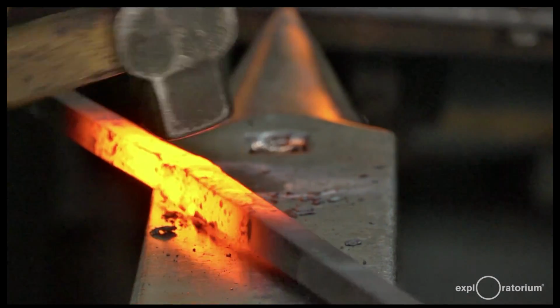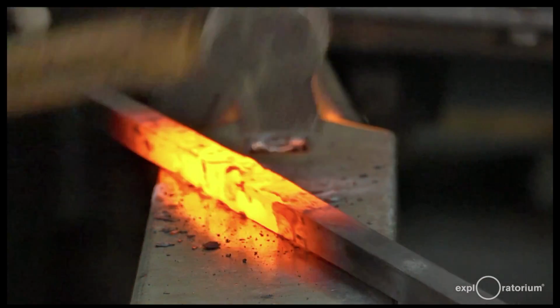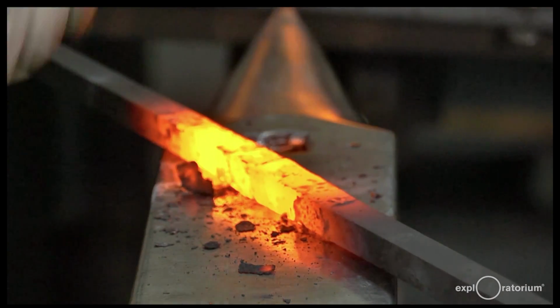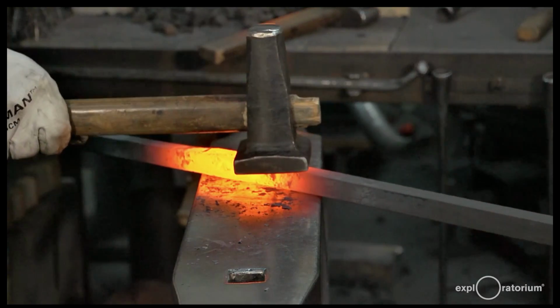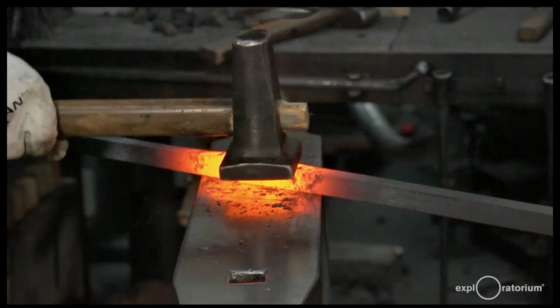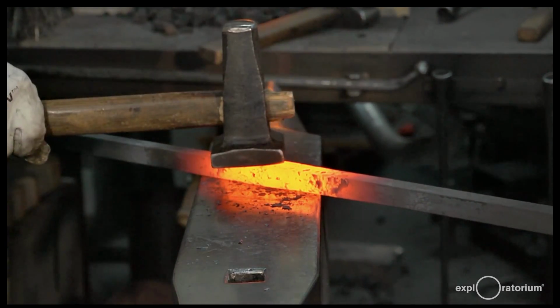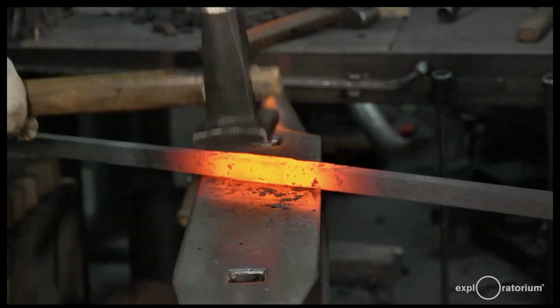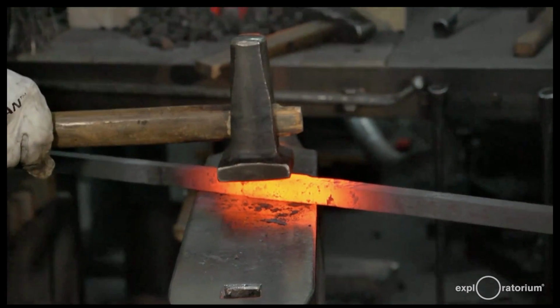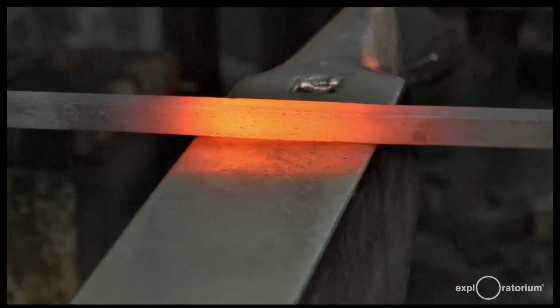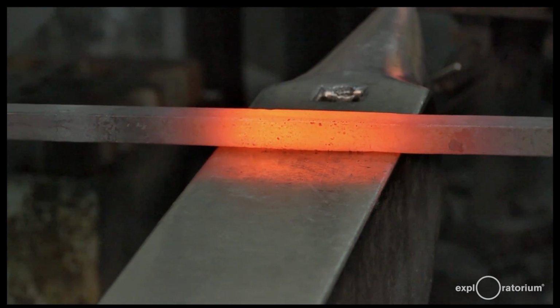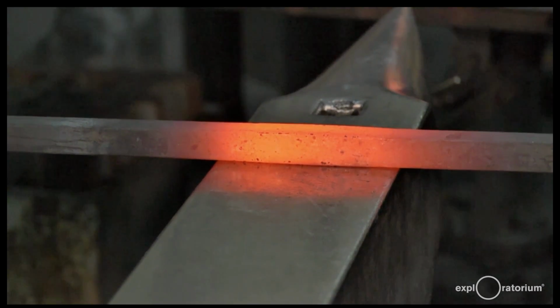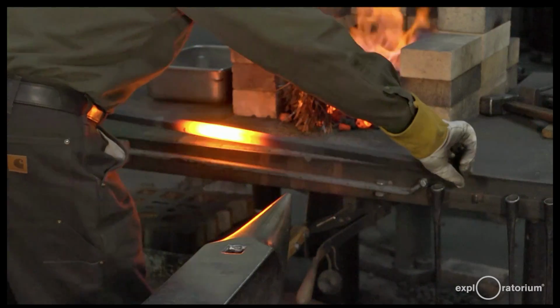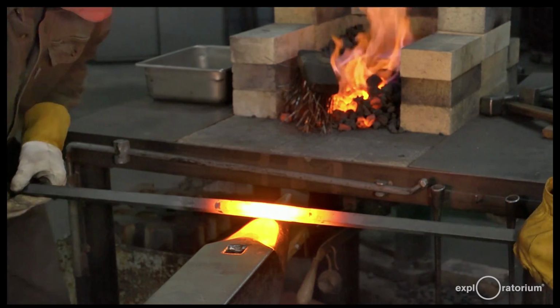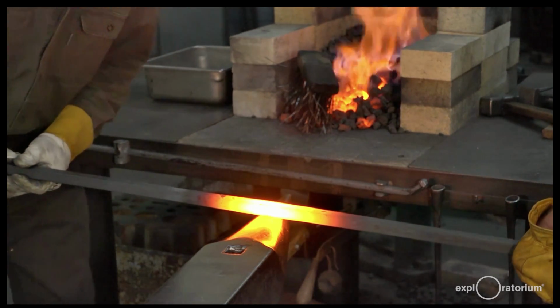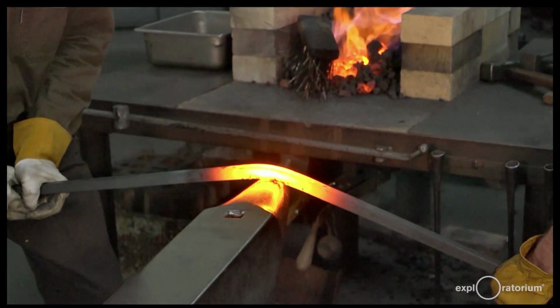After this, we'll be using a tool called a flatter and a sledgehammer to make a much more even shape out of it. And there's the finished weld and the finished bar, and you can see that there's almost no trace of the original seam left. So we'll test it now for you just to help you see what a thorough bond this is.